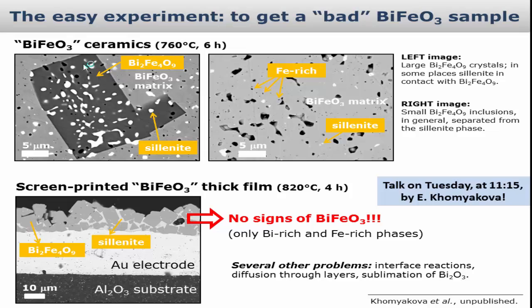When you want to take bismuth ferrite and integrate it on a substrate, let's say with some electrodes, as a thick film, things become even more complex and more difficult. This is, for example, a case when we wanted to deposit BiFeO3 on a substrate. After heating, you get just the secondary phases without any sign of BiFeO3. Here the problems are others: interface reactions, diffusion through layers, and so on. This will be presented in more detail by Genia Komekova on Tuesday, and you will see all these kinds of problems when you want to integrate BiFeO3 materials on a substrate.